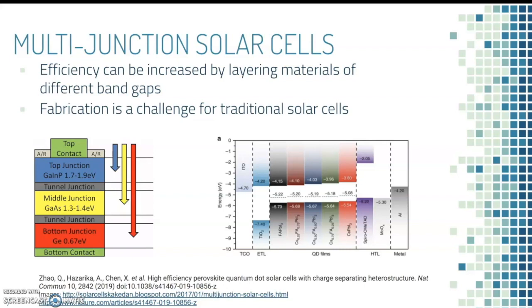But design with quantum dots has not achieved such efficiencies yet. A recent 5-layer quantum dot solar cell reported an efficiency of 15.47%, which is still lower than the 20% efficiency of a single crystal silicon solar cell, which are standard in commercial use. The ease of fabrication could make quantum dots a cost-effective method of fabricating multi-junction solar cells, but there is plenty of research to be done before this concept is realized.